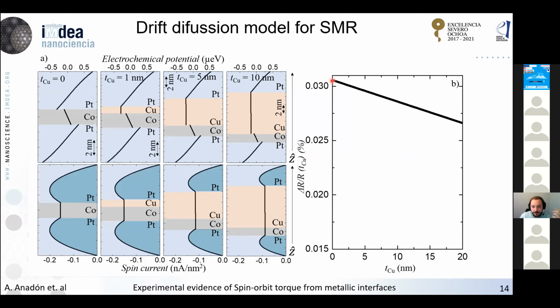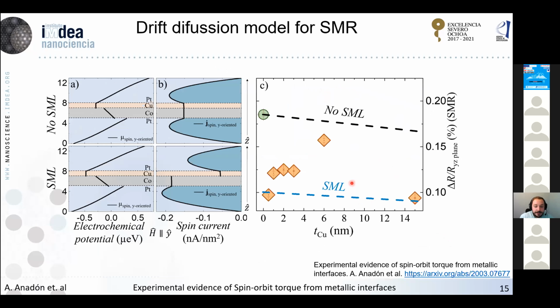As I said before, copper is almost transparent. We see a small decrease of the spin-Hall magnetoresistance of the system when we change the copper thickness up to 20 nanometers. And this bulk drift diffusion does not explain the decrease of the spin-Hall magnetoresistance when we introduce the copper interlayer. So what we did is we introduced spin memory loss, and after introducing the spin memory loss in this copper cobalt interface, we observed that the spin-Hall magnetoresistance was drastically reduced, and the behavior that we are observing mimics very well what we observe experimentally for the sample with half a nanometer of copper.